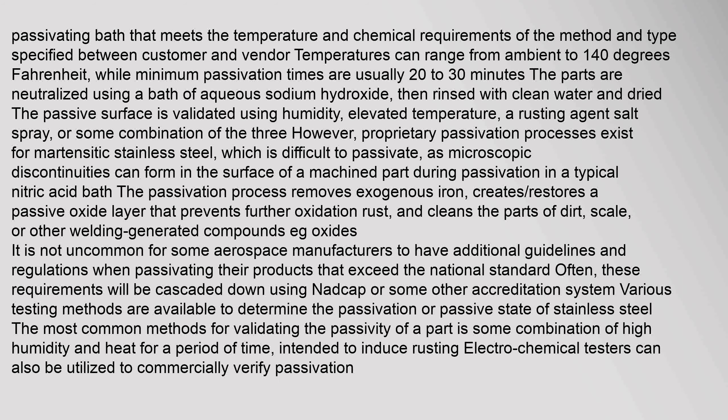The passivation process removes exogenous iron, creates and restores a passive oxide layer that prevents further oxidation and rust, and cleans the parts of dirt, scale, or other welding-generated compounds such as oxides. It is not uncommon for aerospace manufacturers to have additional guidelines exceeding the national standard. Often these requirements will be cascaded down using NADCAP or some other accreditation system. Various testing methods are available to determine the passivation or passive state of stainless steel. The most common methods for validating passivity involve high humidity and heat for a period of time, intended to induce rusting. Electrochemical testers can also be utilized to commercially verify passivation.